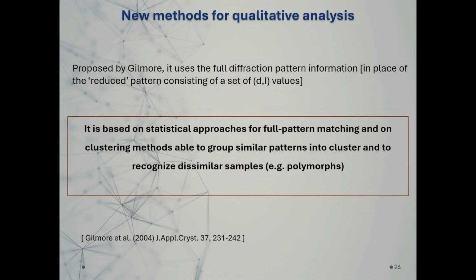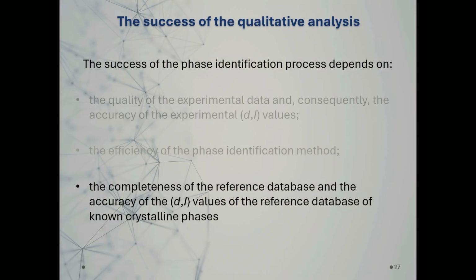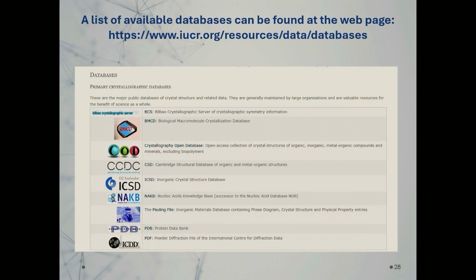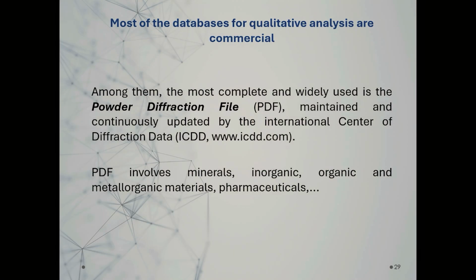So among the new methods for qualitative analysis is the one proposed by Gilmore, which is based on a statistical approach for full pattern matching and on clustering methods able to group similar patterns into clusters and to recognize dissimilar samples, such as polymorphs. And in the end, it's really important the completeness of the reference databases that I'm using and the accuracy of the d-hkl values of the reference database of known crystalline phases. So here there's a list coming from the web page of IUCR, a list of the databases that are the most used today, and one of the most used is a commercially available database.